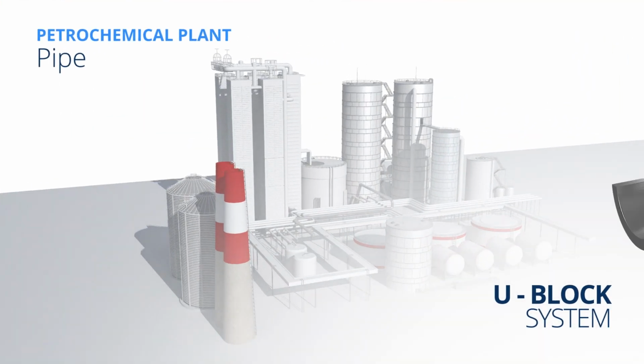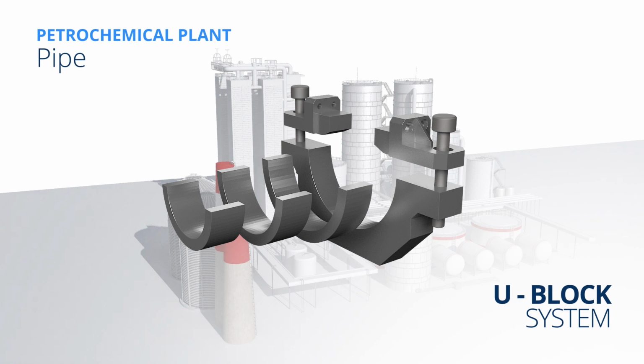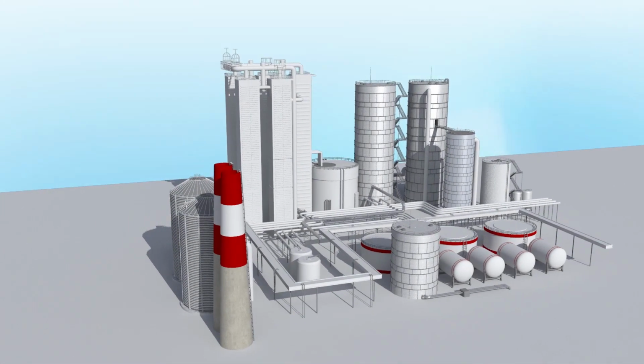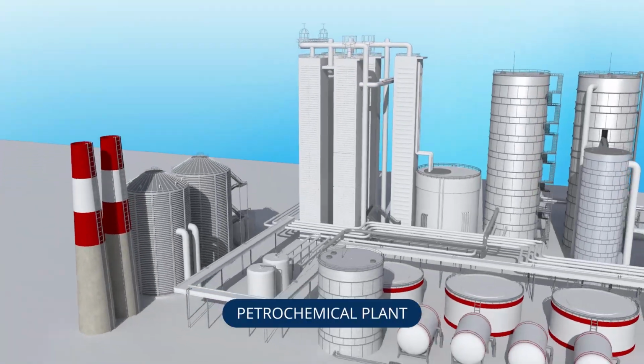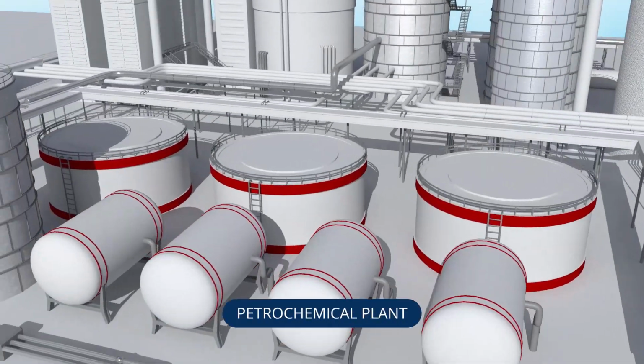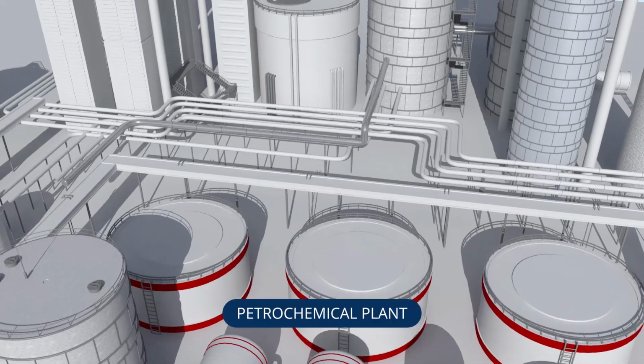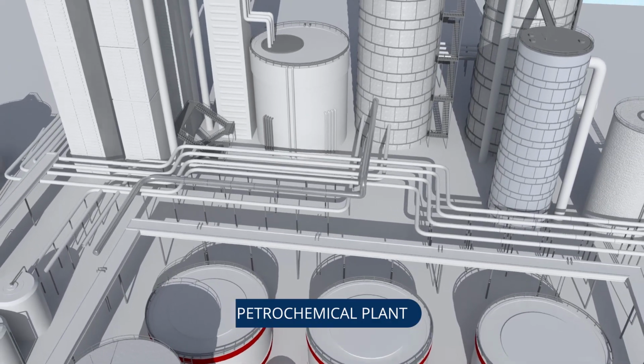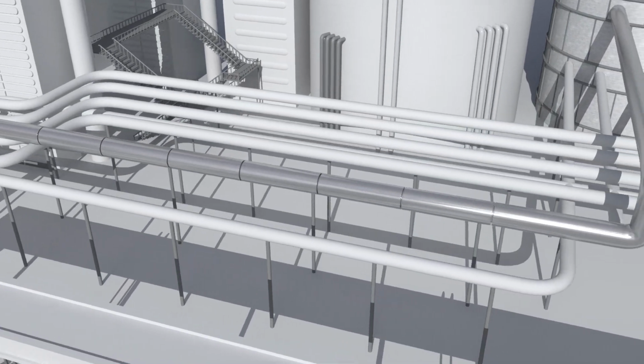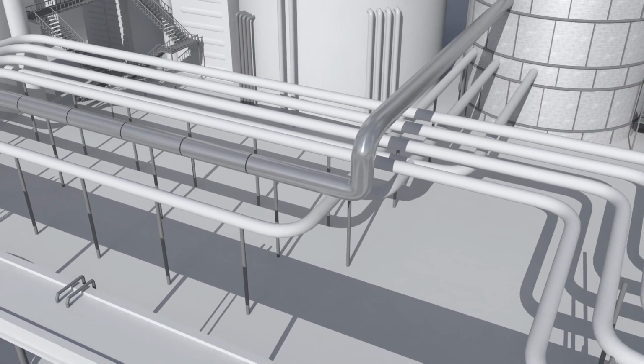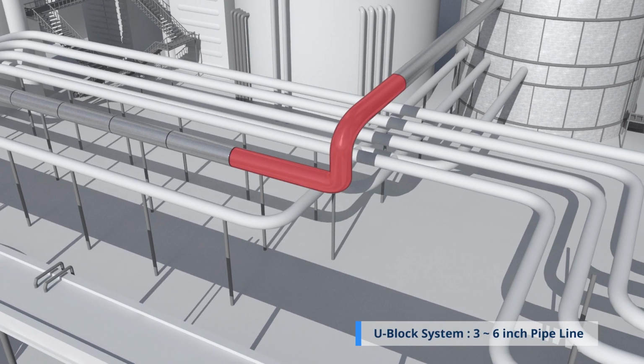The second case to be introduced is a petrochemical plant, and the attachment used is the U-block system. Using a U-shaped block, this attachment is applicable to 3 to 6 inch pipe. The test object is a pipe at a petrochemical plant, and the test is intended to evaluate the deterioration of the pipe over time. Besides, it's applicable to evaluating residual stress on welding pipe.